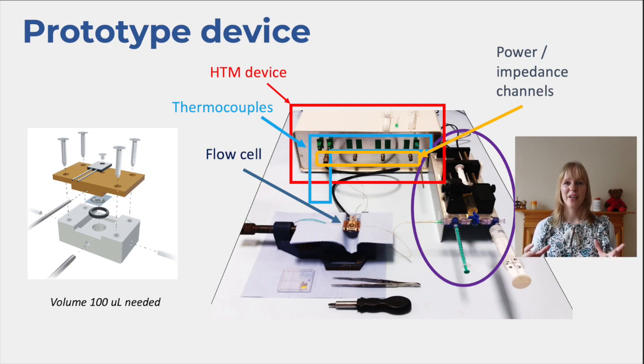Now the actual sensor is very small. When you think of water, obviously you're not so limited in terms of the volumes that you're working with. You can work with a big volume, but typically we work with a flow cell which is around 100 microliters. That's, imagine, the same as 3 drops of something. And then we have a disposable electrode in there, which is called a screen printed electrode. All these electrodes are only a few pence a piece. Very easy, they're completely disposable. You slot your electrode in there, you measure, and then for the next measurement you move on to the next electrode.